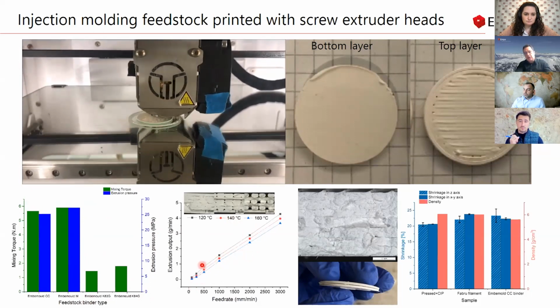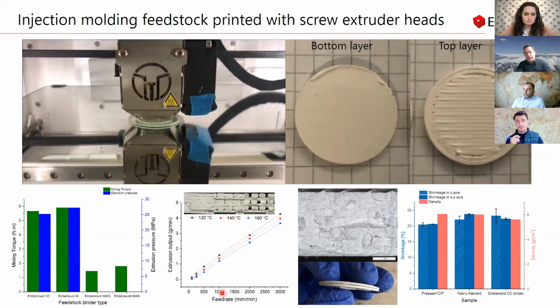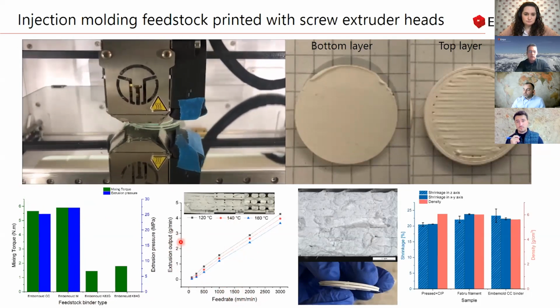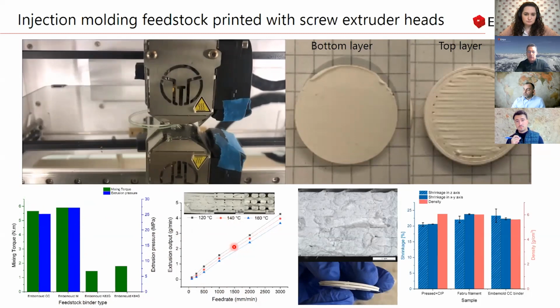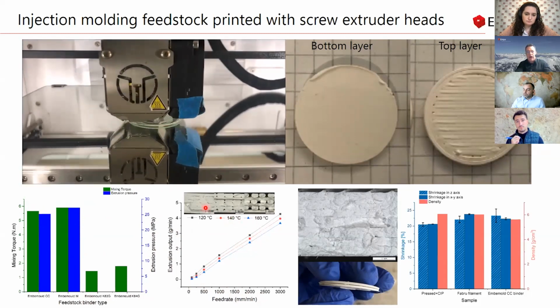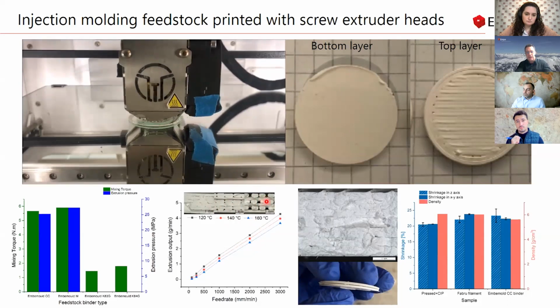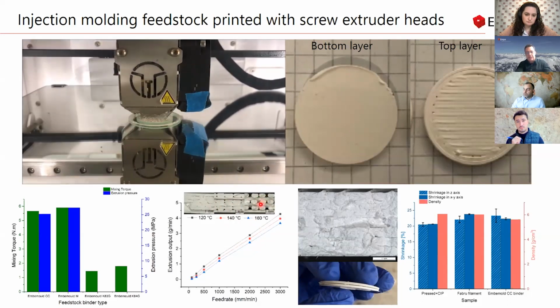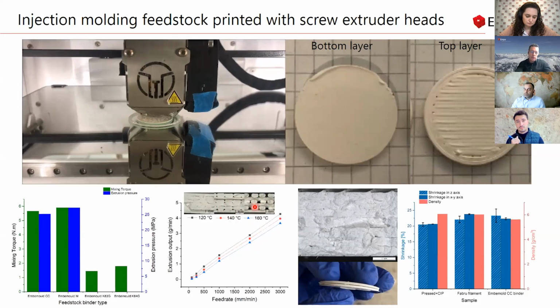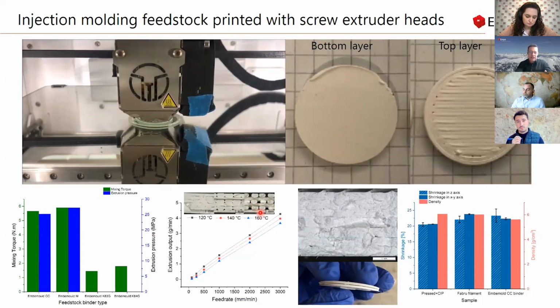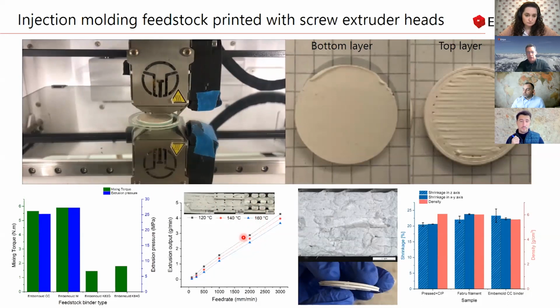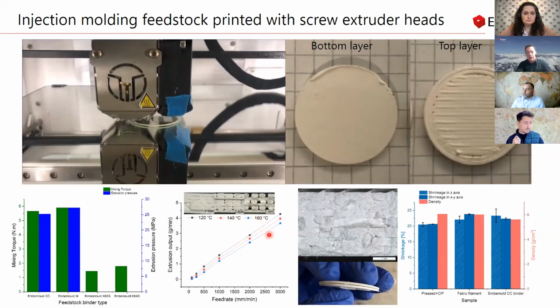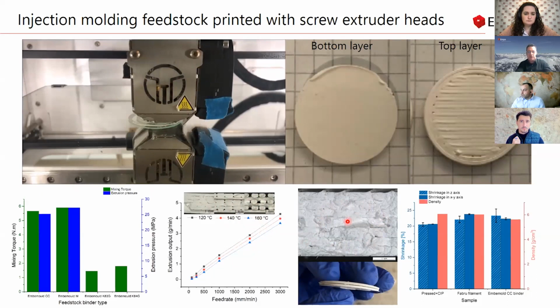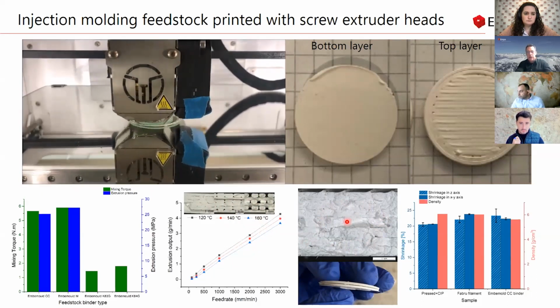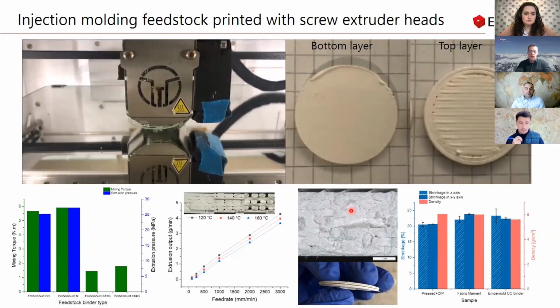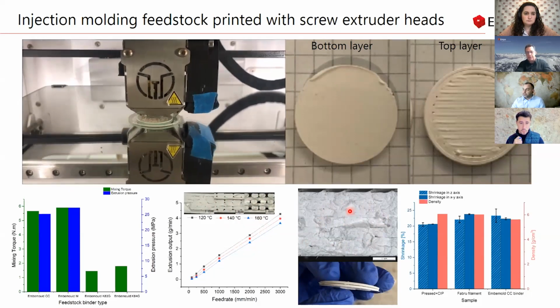So you can see here that you have a nice linear relationship between the feeding rate and the extrusion output. However, one thing has to be mentioned, that when we go for high speed, we lose a little bit of the densification with this kind of printers. So this is something we still have to investigate further, so that even when we go with high speed, we can keep a very dense structure, as you can see here, because this is clearly needed when you want good mechanical properties for metals or ceramic parts.